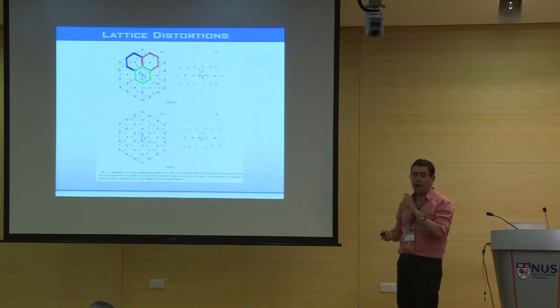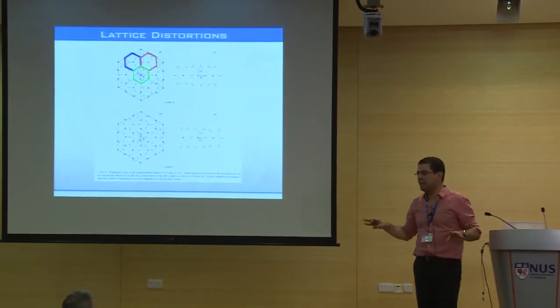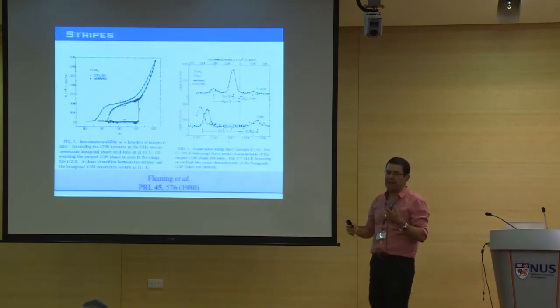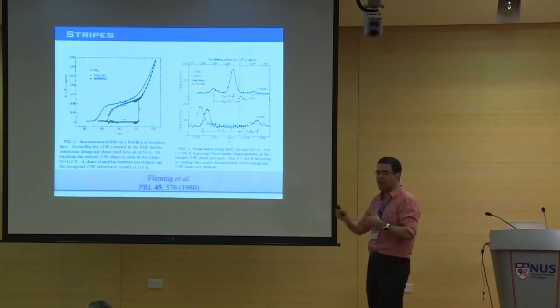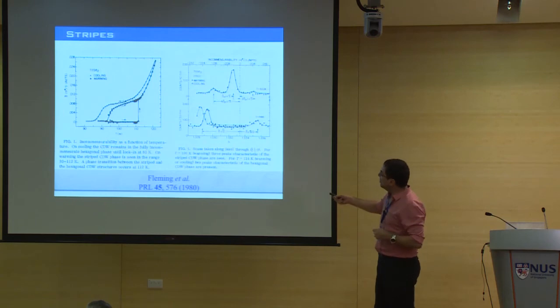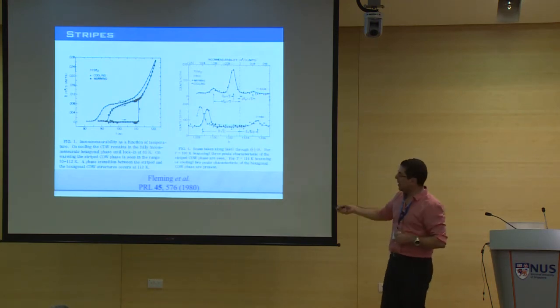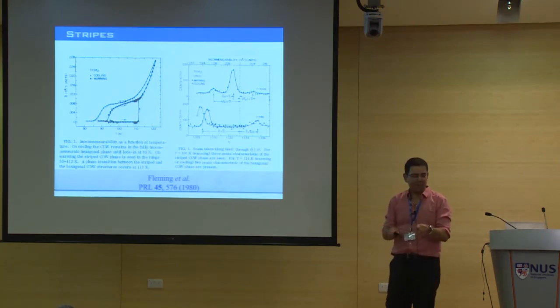So, and this is all happening in plane. So the out-of-plane physics is almost irrelevant for these materials. Okay? And actually, if you look at the stripe phase, because I showed you a stripe phase, what's a stripe phase? It's very interesting. It has to do with this phase difference between these wave vectors. This is tantalum diselenide. On cooling, you see the transition I was talking about. So you go through an incommensurate phase into a commensurate phase. But when you warm the sample, on the way back, it has a hysteresis. So 2 of the wave vectors lock in, but the 3rd one doesn't.